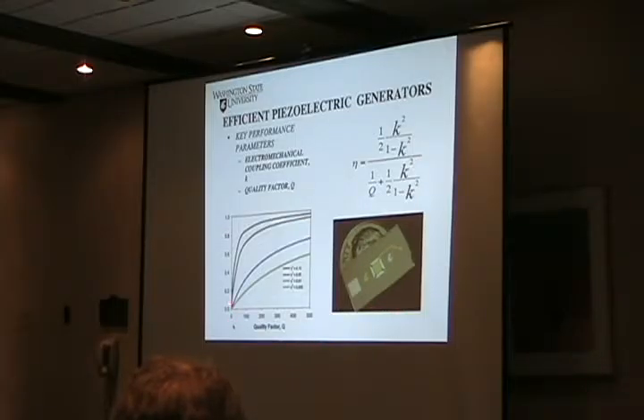And the overall efficiency of a resonating cavity of that sort of structure, if we end up with something like a Q of 100, well, we're going to be about 10% efficient for mechanical to electrical. And for most of the materials we're using, we actually have a K squared somewhere around 5 to 10%. And so that should put us up kind of in the 30 to 40% mechanical to electrical conversion.